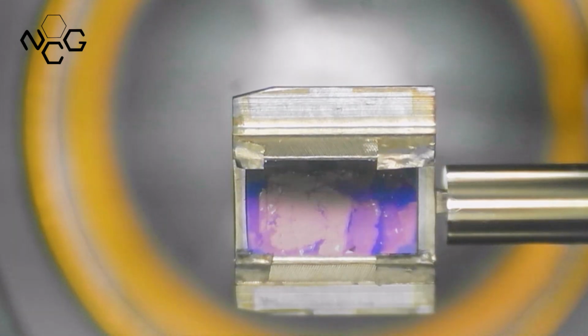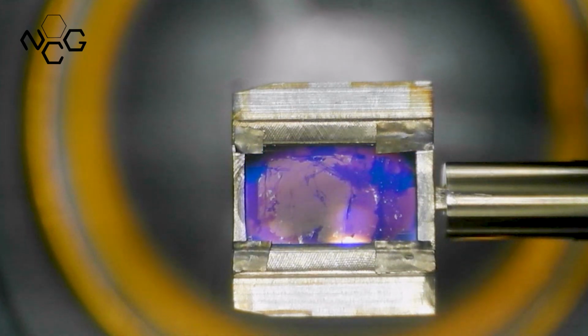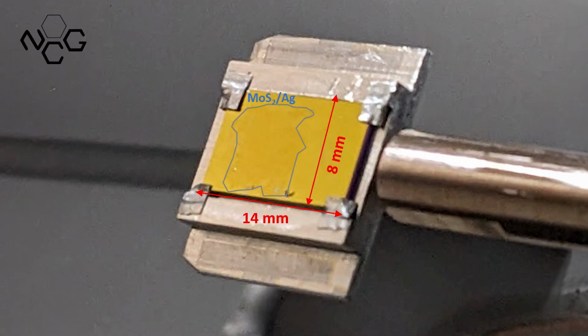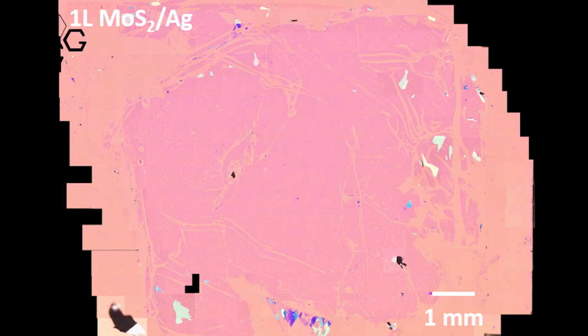The surface of silver oxidizes fast, so exfoliation in air is challenging. In UHV, we obtained results similar to gold. MoS2 flakes of several millimeters, mostly monolayer and single crystal. So here is where our system proved effective.